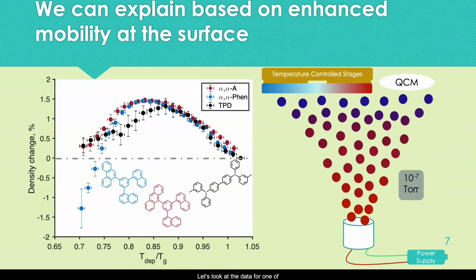If we look at the data for one of these systems or a few of these systems, we can look at the density change as compared to liquid quenched for these three organic glass formers that are commonly used in this lab. And what you see is that at particularly low temperatures or at particularly high temperatures, we don't really see that much enhanced density. But in the middle, between 0.8 and 0.9 Tg, we see this enhanced density change on the order of 1.5% relative to ordinary liquid quenched glass.